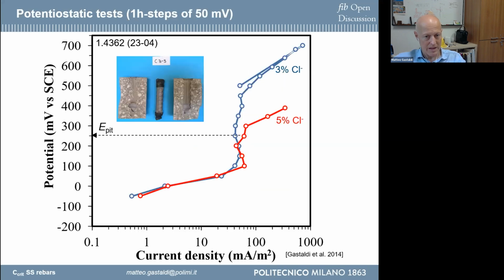This is, for example, an example of some results related to laboratory tests related to this kind of procedure. This is the test in which we have different samples with a fixed amount of chloride, and the potential is increased in time with a step of 1 hour. Sorry, the increase of potential is 50 millivolts in steps of one hour. So each hour the potential is increased by 50 millivolts.